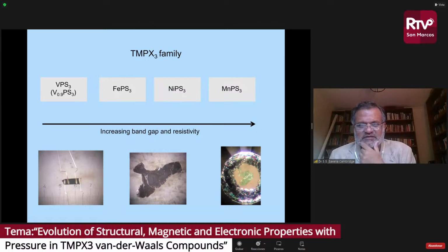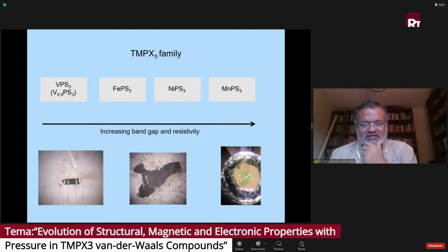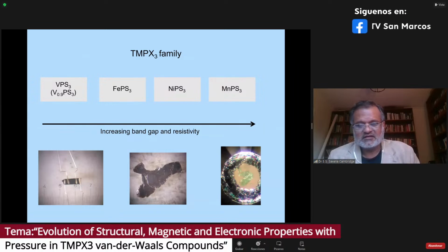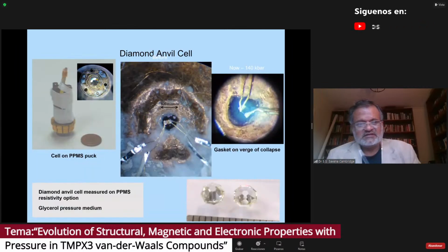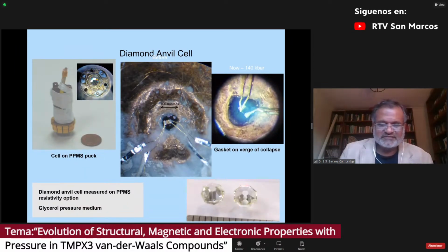So you have this general family of, for instance, FePS3, nickel PS3, manganese PS3. There's some other, cobalt and others as well. But these are the ones we have studied in recent days. And you can see how the band gap increases, and that will become relevant in the data I'll show you in a second. We were able to handle them well. We were able to put 4-point contacts onto them, and we were able to do high pressure experiments,